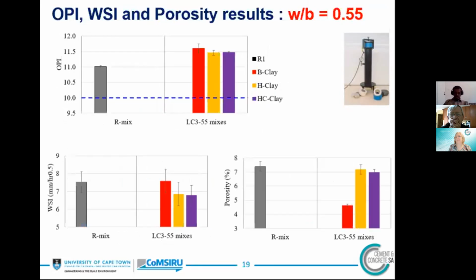Now this is the case of 0.55 water binder ratio. Again, here we have the same story. LC3 mixes are better than the reference mix. Then here similar sorptivity, and the porosity similar or better than the reference mix.